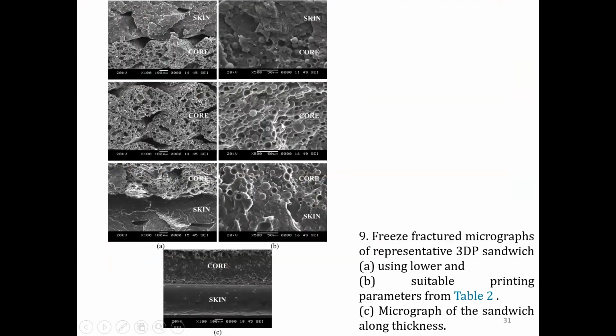So once we print it with suitable printing parameters, you can see a lower skin and a core, and you can see the transition between these two. As there is a seamless interface between the skin and the core, there is definitely not going to be delamination between the skin and the core, which is a most common phenomenon in conventional sandwiches. So with that thought process we worked on this.